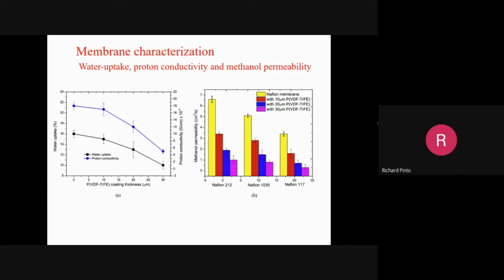You see here, the red one is 10 micron thick, then blue is 20 micron. So permeability goes down as you increase the thickness. Suppose you take 212, this is 50 micron thick, permeability is more or less the same as the 183 micron thick membrane. Okay, so this is the advantage. So you reduce the methanol permeability without much affecting the proton conductivity.